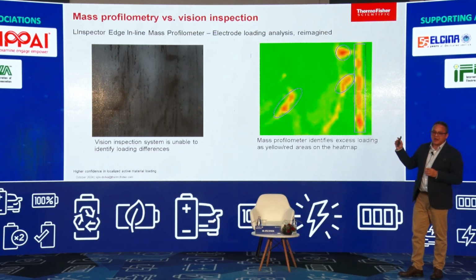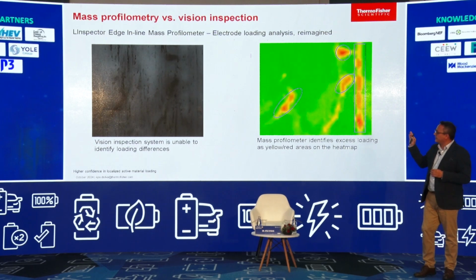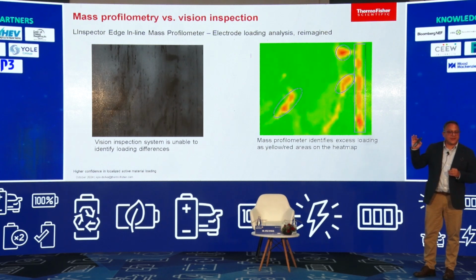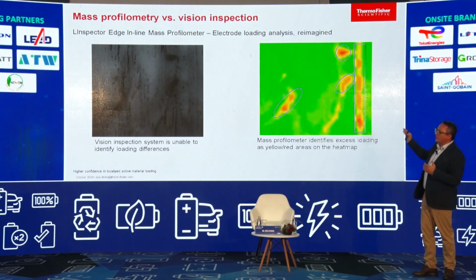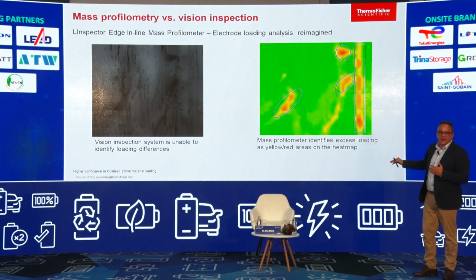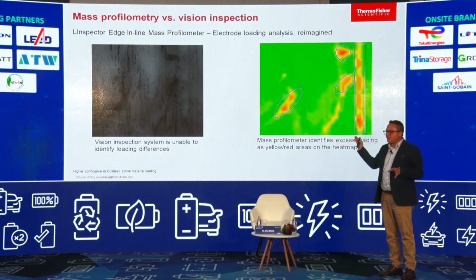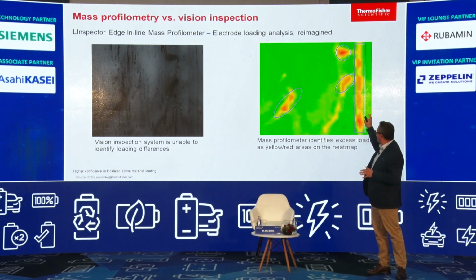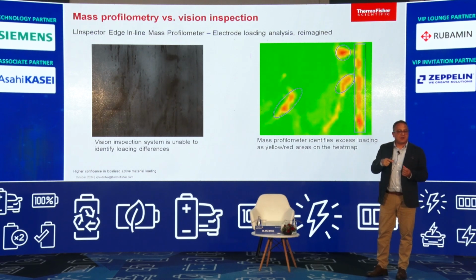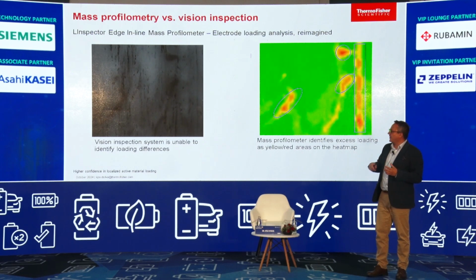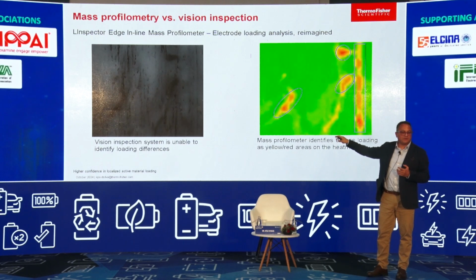So here we can see some areas of dark patches. We don't know if they're thick or thin. On the right-hand side, we can see some patches that the machine has detected that are thick. They're out of specification. But draw your attention to the long strip on the right-hand side. The long strip is unfortunately a large area of thick material out of specification that you could never detect through visual inspection. So it shows that it's a complementary technique to existing visual inspection, but it goes one step further to give you extra confidence.